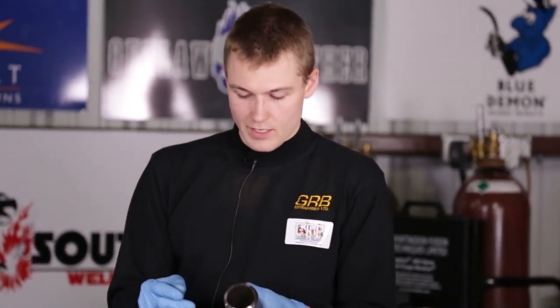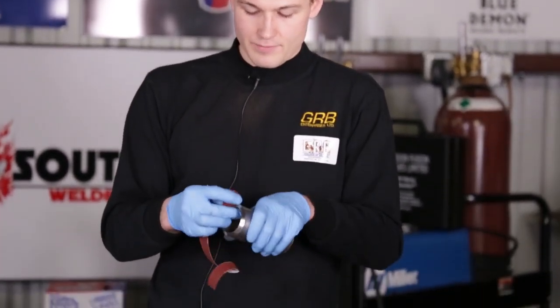Always use what you're using right here. Essentially on titanium, use cold working means. Don't use a grinder, because a grinder also hardens the material that you're grinding into, and if you do a hardness test on the material you've used the grinder on, it'll show that it's been hardened. Also, friction from the grinder creates heat. It starts to oxidize, and it's going to embed oxides into the material. So when you weld over that material, you're going to have a lot of problems.